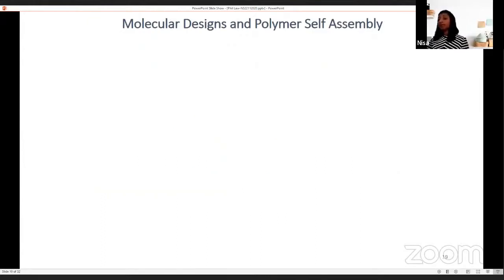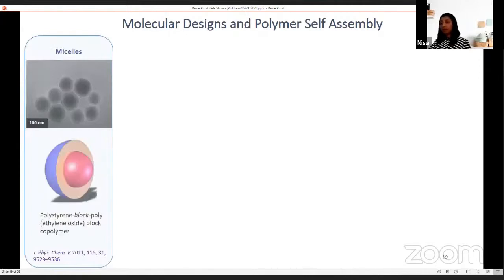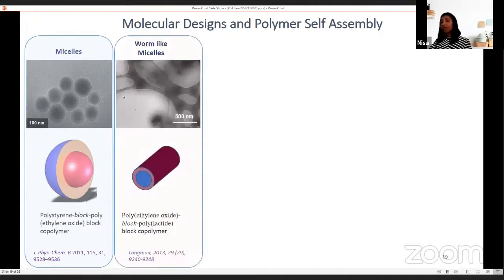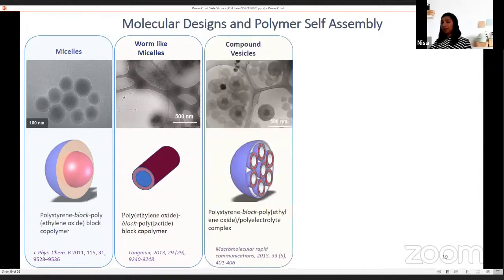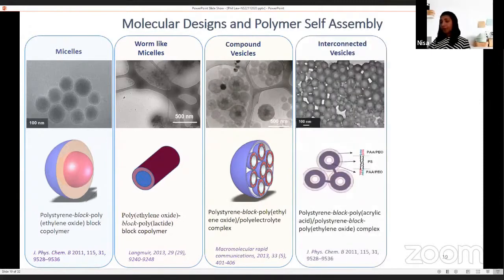I'm going to show you some examples of nanostructures we created in our research using block polymer self-assembly. These are spherical structures formed from a diblock polymer. Here the polystyrene chains form the core and PEO forms the shell. In this study, we came up with very unique thread-like micelles formed by block polymer self-assembly. We also prepared compound vesicles for the first time by using a mix of polymers and polyelectrolyte complexes. As you can see, the structure consists of many tiny vesicles encapsulated inside a giant vesicle. We also prepared interconnected vesicles, where you can see the channels connected using polymer chains.